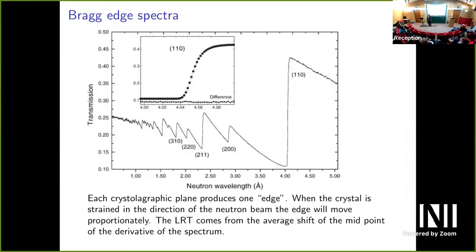Of course, it's not so true in metals, because usually the whole point of metallurgy is to align the crystals in some direction. But you know, there's like a really annealed piece of metal. And what we assume is, for the width of the beam, we have a notional kind of voxel size, about the size of the beam. And over that beam, we've got every direction of crystal, so it's random on that scale. It's hard to actually get that. There's a sweet spot. If you use a bigger beam, there's a lower spatial resolution, but you've got a bigger sample of random directions for the crystals. So that's the sweet spot.